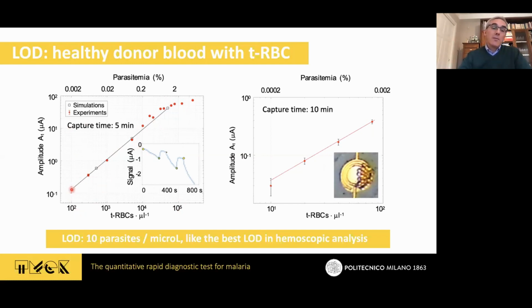And limit of detection in this case was just 100 treated red blood cells, which means 100 parasites per microliter in terms of malaria words. But okay, if you want to increase now the sensitivity or decrease the limit of detection, we can just increase the capture time from 5 minutes to 10 minutes. And you see that we can now reach the 10 parasites per microliter, which is not negligible at all, because it is like the best limit of detection in hemoscopic analysis, 20 times better than currently used rapid diagnostic tests based on antigen detection. And it's really in the order of magnitude of what is looked for also by big agencies like World Health Organization or FIND.